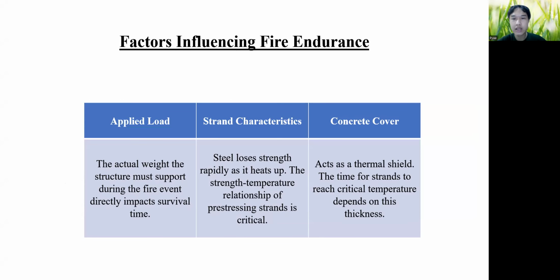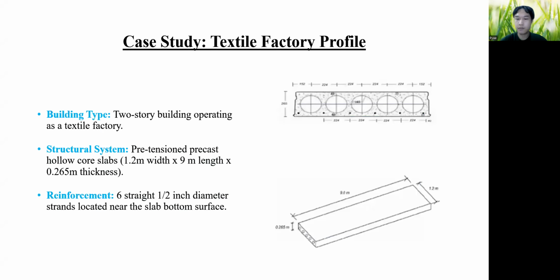Further factors influencing fire endurance: applied load, strand characteristics, and concrete cover. Applied load, the actual weight of the structure that it supports during the fire event, directly impacts survival time. Another one, strand characteristics. Steel loses strength rapidly at high temperatures, so the strength-temperature relationship of prestressing steel is critical. And the third one, concrete cover. The concrete cover acts as a thermal shield. So the time for the steel to reach critical temperature depends on its thickness.